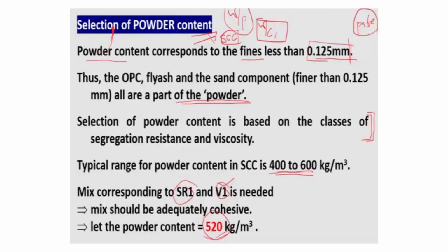Now let us select the powder content. Powder content is the total of OPC, fly ash and the sand component which is smaller than 0.125 millimeter. So powder content corresponds to the fines less than 0.125 mm; basically it will be OPC, fly ash and sand component finer than 0.125 mm. Selection of powder content is based on the classes of segregation resistance and viscosity. Based on this the powder content is selected. The typical range for powder content in SCC is 400 to 600 kg per meter cube.